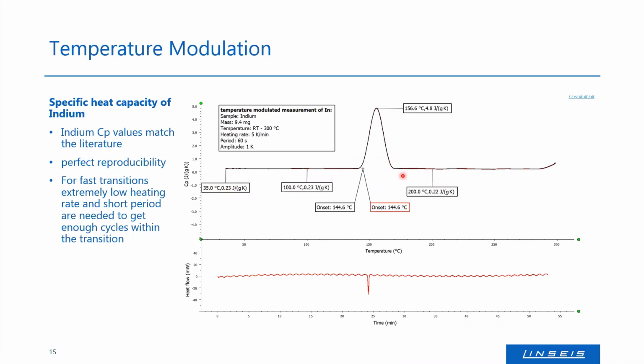What we can also see here is the melting peak again, and also here the CP isn't defined. What's also interesting here is the reproducibility. I'm not sure if you can see it, but these are two different measurements I've performed, so the reproducibility is pretty good. And what you can also see here is that we receive good results also at 35 degrees. I've mentioned the slide before, so I think that's a pretty cool thing, and this is the reason why the Chip-DSC works so well with temperature modulation.